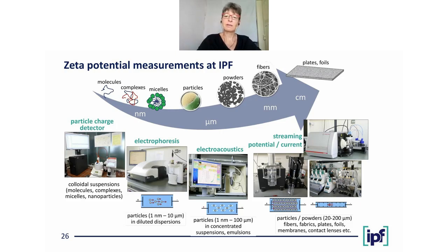A method that is not so familiar is the DT 1200 used for electroacoustics measurements. Here the particles do not move like in electrophoresis, but are moved by ultrasound, and we measure an alternating current resulting from the motion. And this method allows us to measure the zeta potential of larger particles than with electrophoresis, and especially for particles in concentrated suspensions and emulsions up to 50 weight%.